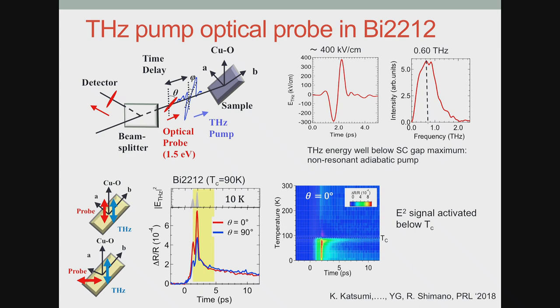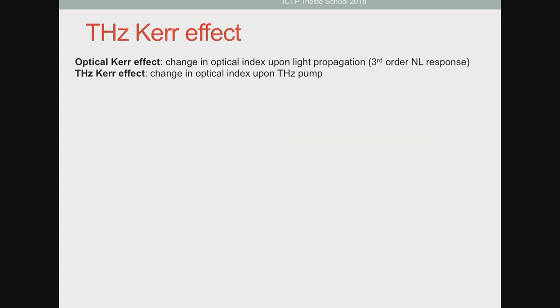And this signal follows the square of the pump. For a given configuration, you can plot it as a function of temperature. And what you see is that this E squared signal indeed shoots up below TC. So it's really associated with the superconducting state.